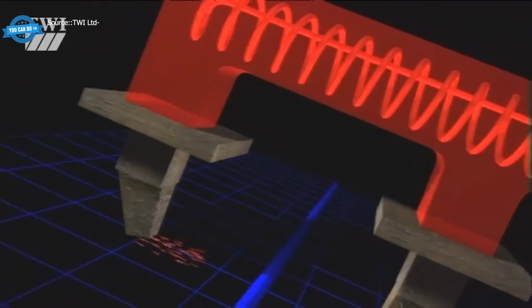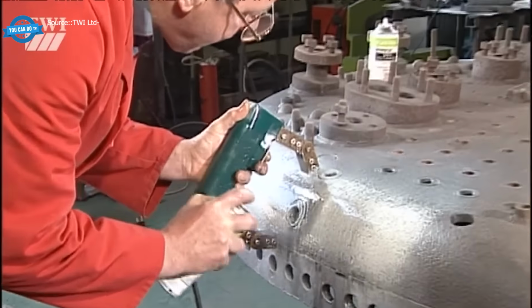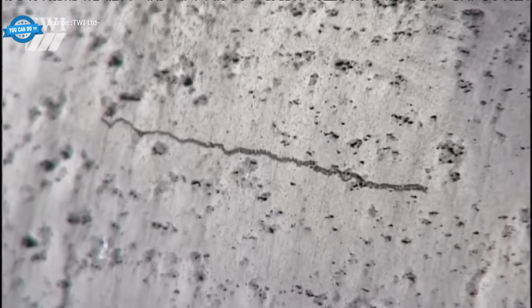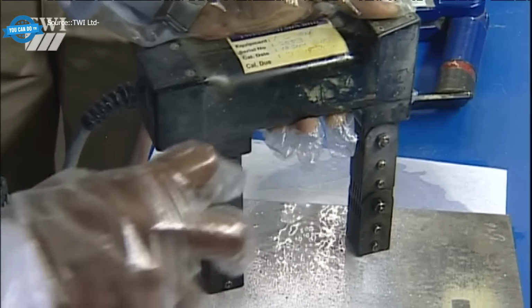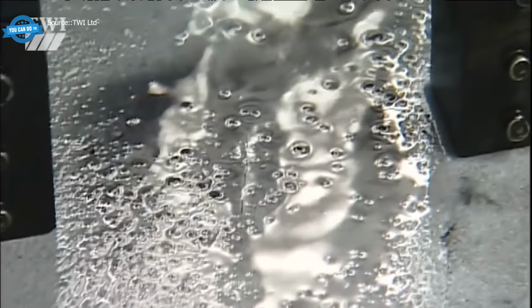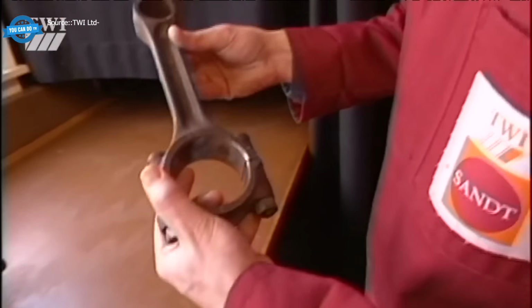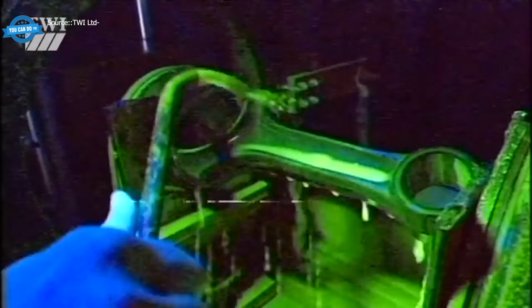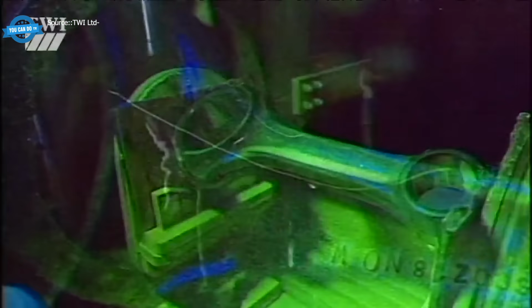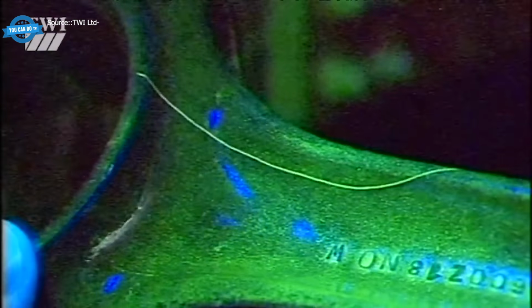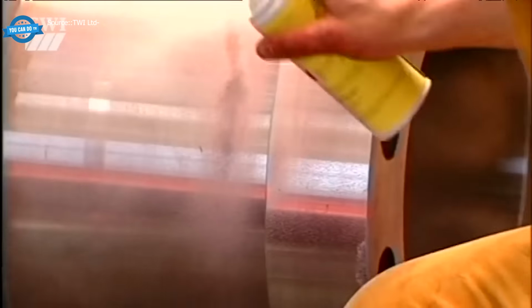Magnetic particle inspection works only on ferromagnetic materials. A magnetic field is applied to the casting, then fine iron particles suspended in ink or fluorescent liquid are dusted onto the surface. Wherever there's a crack or a discontinuity, the magnetic flux leaks and drags the particles into the flaw. Under UV light, the crack lights up bright green against the dark surface. A defect nobody could see suddenly looks like it is drawn in highlighter.